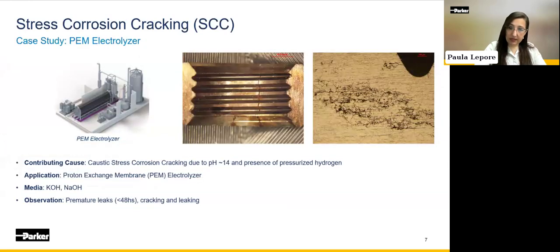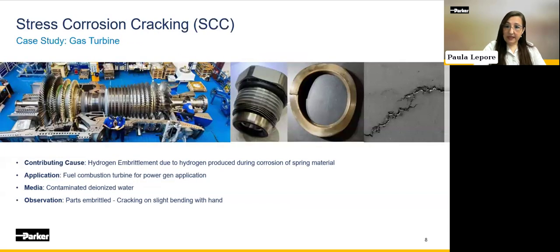One other example close to the clean tech world is a PEM electrolyzer, where parts are submitted to high concentration of caustic media at high temperatures, showing accelerated degradation, sometimes as fast as 48 hours of operation. This is a classic example of stress corrosion cracking, or caustic SCC. Yet another compelling example in the energy market is the hydrogen embrittlement of components of a gas turbine, where hydrogen embrittlement was caused by contamination of the media or deionized water, where combustion gases were being backflushed through the hydraulic circuit, causing premature failure.